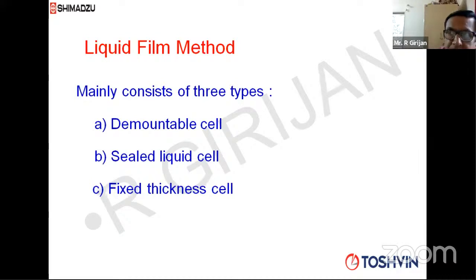And you can open this. You can put 1 drop of a liquid on 1 crystal and put another crystal over that. Slightly press it, so it will spread like a thin film. And there's a holder. You can record the spectrum of the liquid sample qualitatively using the demountable cell. Demountable cell means the crystals can be separated. You can open the cell, and the crystals can be taken out separately. After use, you can wash it, and you have to keep it in a desiccator. You keep it always under desiccation, because many of the cells are very, very susceptible to moisture.